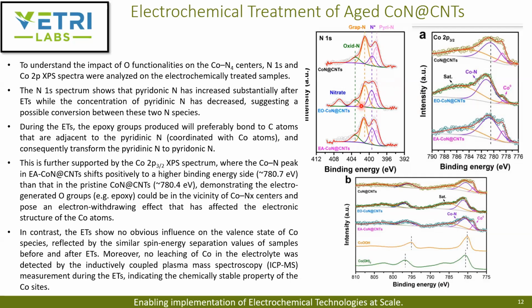Then they also looked at the cobalt 2p 3/2 spectra. What they can see is the cobalt nitrogen peak shifted positively to a higher binding energy on the electrochemically activated catalyst, demonstrating that the electro-generated oxygen groups impose an electron withdrawing effect that affected the electronic structure of these cobalt atoms. However, in contrast, the electrochemical treatment did not show any obvious influence on the valency state of cobalt. As we can see here, it still almost remains the same, and it was not +2 or +3 based on their standards here.